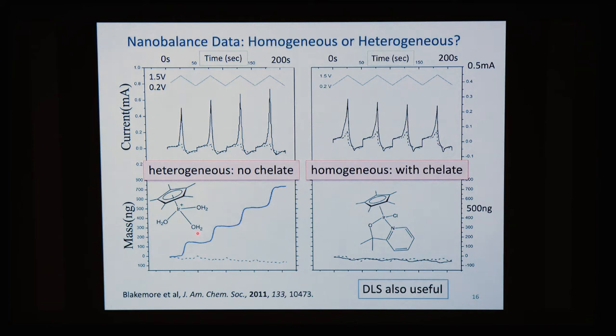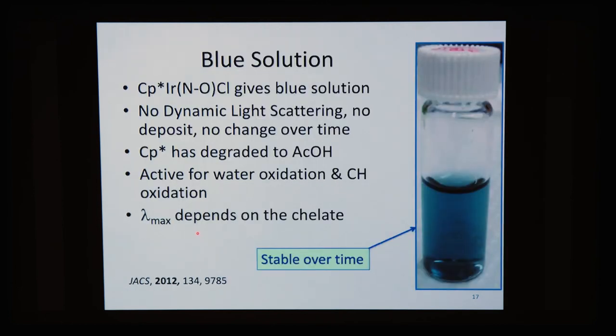So James was able to show the effect of the ligand in preventing heterogeneous catalysis. And here is the blue solution. No dynamic light scattering, no deposit, no change over time. And the CP star has degraded to 1.8 equivalents of acetic acid. And this is active for water oxidation and CH oxidation. And the UV visible lambda max depends on the chelate. And therefore, that's the first indication that the chelate is still bound.